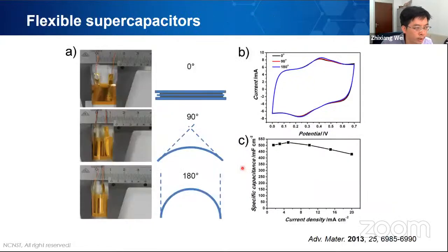With this, we can really assemble flexible supercapacitors. You can see we just stack two layers together, and this flexible supercapacitor shows really good cycling performance with different bending angles, from 0 degrees to 90 degrees to 180 degrees. And you can see it still has really good capacitance and also high rate performance. That means you can charge with high current density, and the capacitance is kept very high.